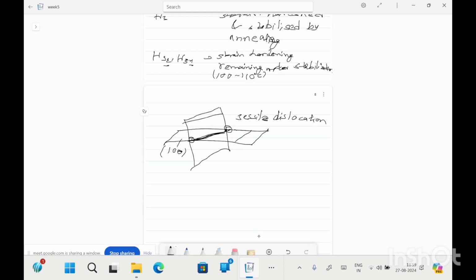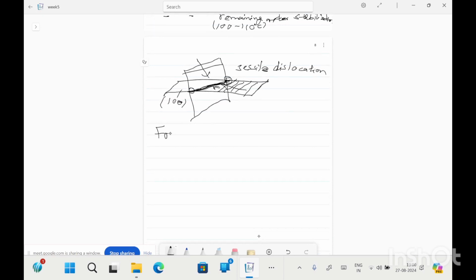Because of the formation of the sessile dislocation, further dislocations coming to this plane will agglomerate at the sessile dislocation, impose stress, and increase the strength further. This is the Lomer-Cottrell lock. Second is the formation of jogs and kinks.